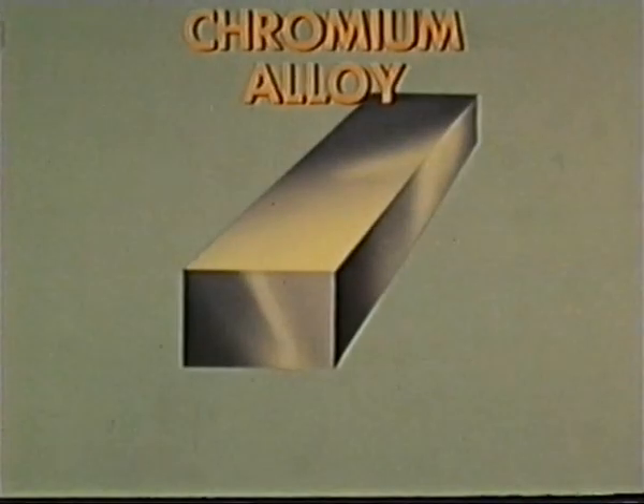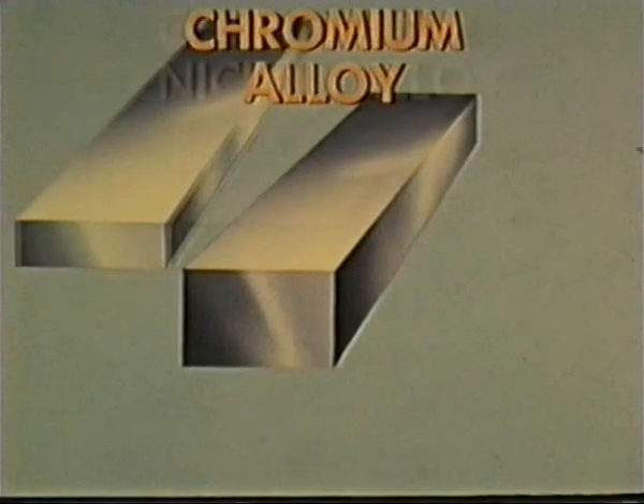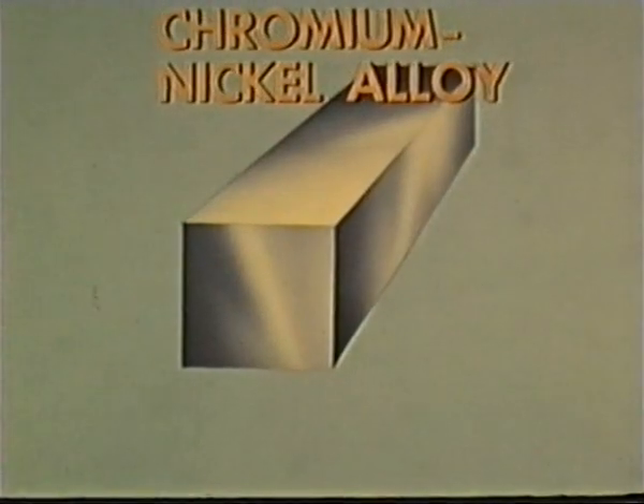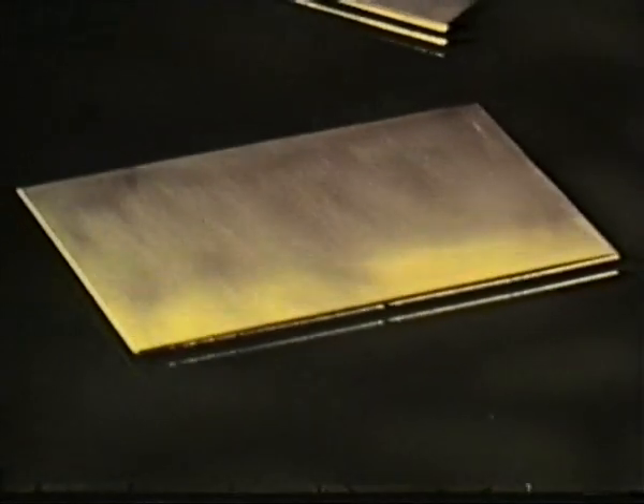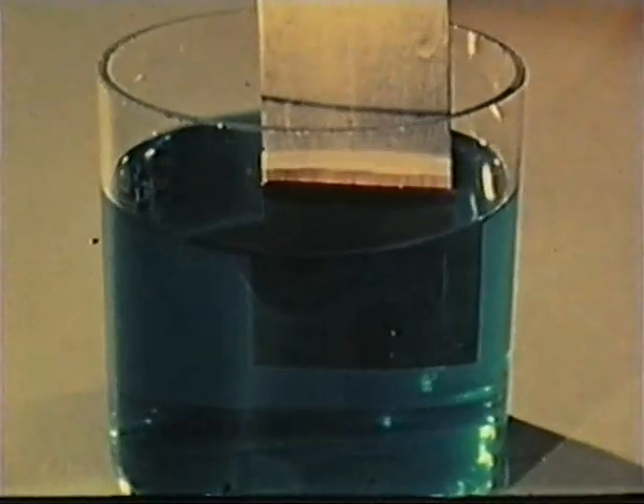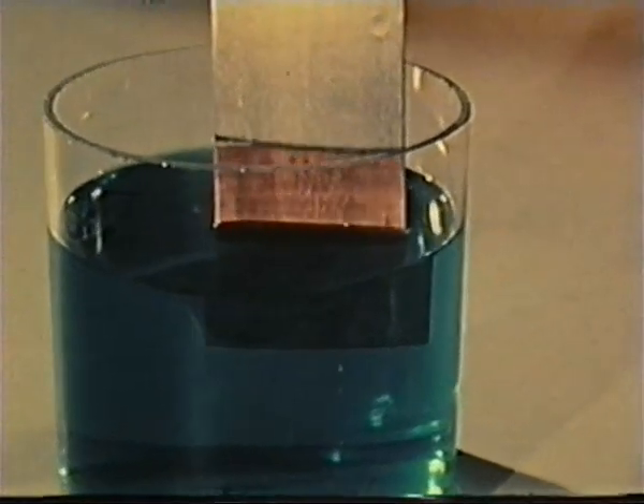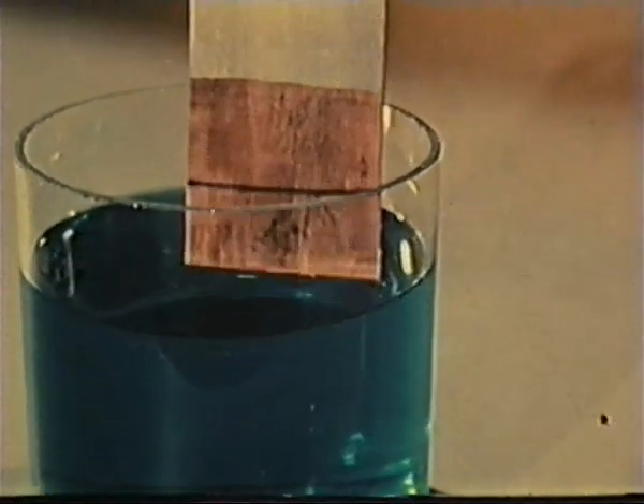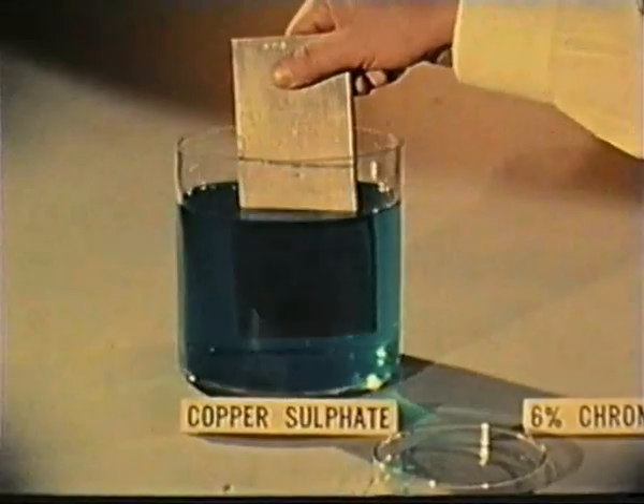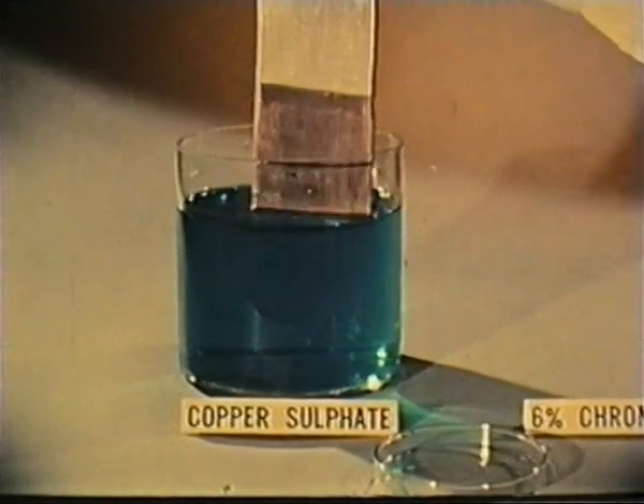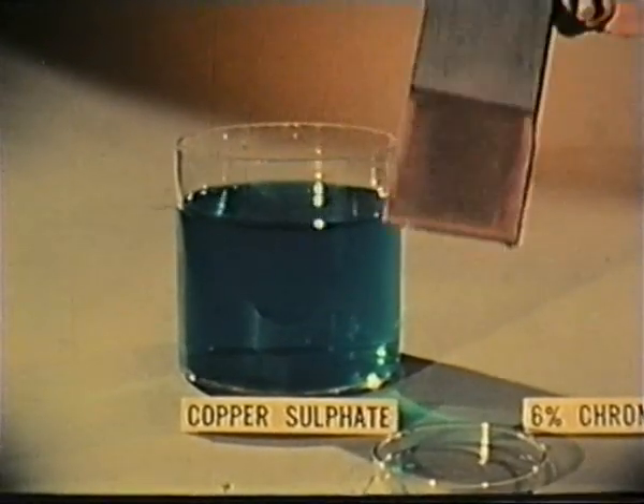By alloying iron with chromium or a combination of chromium and nickel, the alloys develop a much more stable passivity, such as we have in stainless steels. Whether these iron-chromium and iron-chromium-nickel alloys are active or passive depends on their composition and the environment. Iron with 3% of chromium is active in copper sulfate solution and plates out copper. With 6% chromium, the plating out is proceeding more slowly, but the alloy is still active.